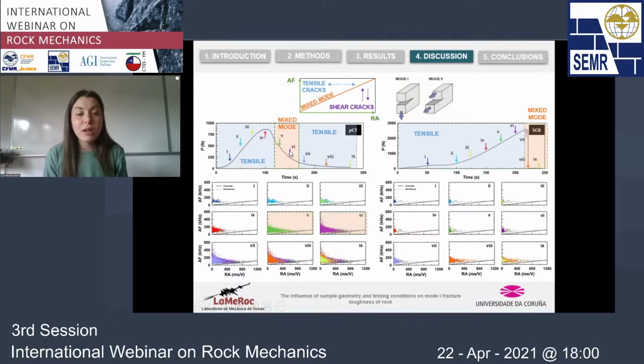And this is due to the propagation of the cracks, which do not always follow the vertical plane, but try to avoid the higher density grains. So we can have mixed mode conditions. For the SCB, we observe something similar: up to peak load, all the events are in the tensile field, but at specimen failure at peak load, the events are also recorded under mixed mode conditions.